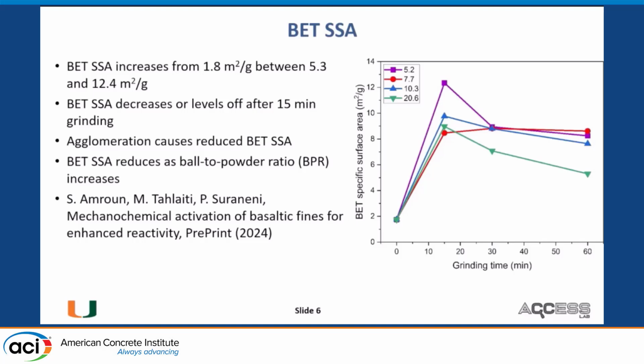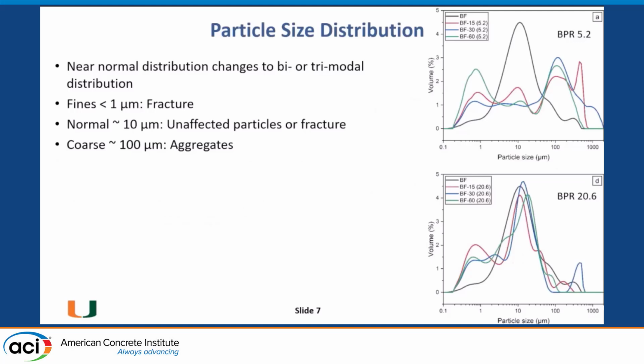So anyway, the specific surface area increases from about 2 to between 5 and 12. So it's a very significant increase in surface area. And of course, you increase reactivity by increasing the surface area, maybe. So we see a little bit of a trend that the specific surface area reduces as the BPR increases. If you're interested, a preprint is available on ResearchGate and SSRN, but I'm also happy to send you the paper. Let me know.